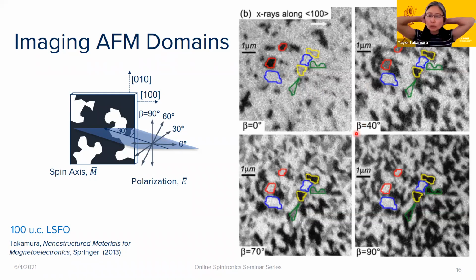And so what we'll get are then a series of images here. So this is going from beta equals 0 when it's canting out of plane, and then going to beta equals 90 degrees where it's vertical. And so what you'll see is that as we change that polarization angle, what I did is color code a few regions of interest, right? And so if you follow them, for example, with the blue domain, this blue domain stays white, regardless of what the polarization angle is.